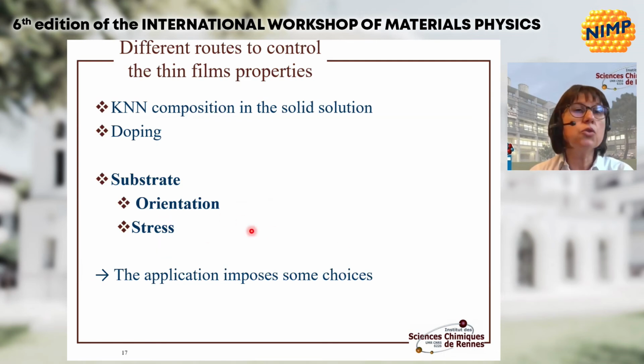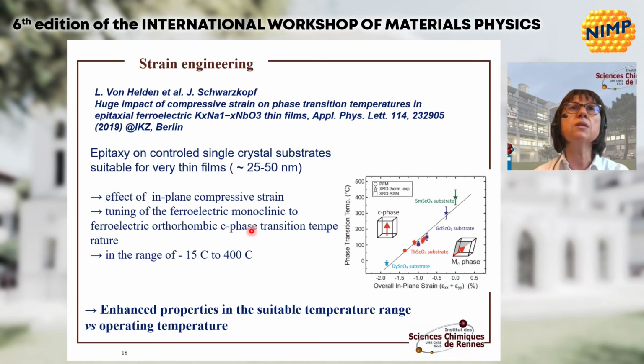Another possibility is to tune the properties of the material by the substrate, and especially by stress and orientation. You can see the example of the work performed at IKZ in Berlin, in the group of Jutta Schwarzkopf, by changing and monitoring the strains. In this lab, they developed single crystal substrates with appropriate lattice parameters, depending on the composition of the KNN system, in order to control the strain.